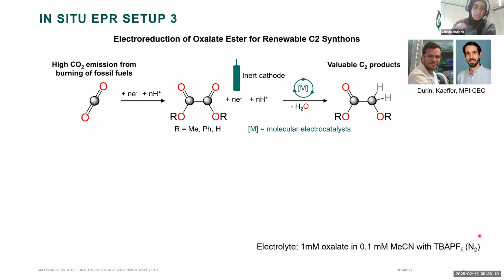But that was a test subject to see that everything was working. But to go further, we worked with our collaborators here at the MPI CEC, so Durin and Nicholas Kafer, where they were looking at the conversion of CO2 into these C2 products. The mechanism of this was unknown to them, but they speculated that it goes through a radical. And so we thought we could use the spectroelectrochemical setup to study this.